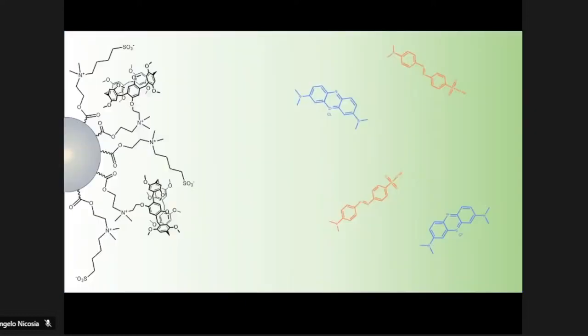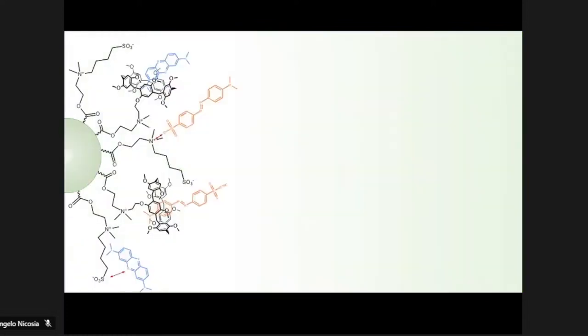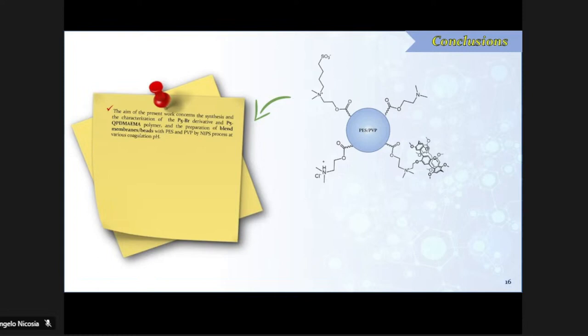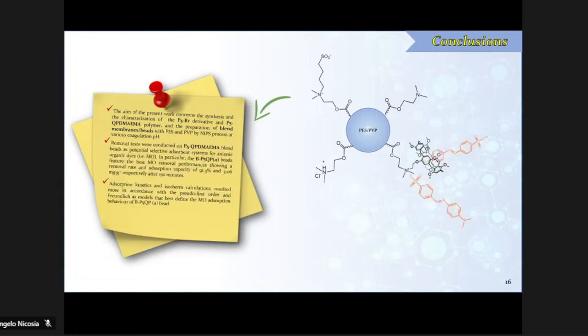So this is the mechanism towards the removal of both dyes by the zwitterionic bead. So again, possible host-guest interaction and electrostatic interactions between the beads and the dyes. In conclusion, we were able to obtain different functional beads, fully characterized also by XPS measurements, and we were able to perform different adsorption experiments to understand their adsorption behavior, confirming that the P5 based bead was the best one for the retention of the anionic dye methyl orange, as well as a zwitterionic bead able to retain both anionic and cationic dyes. Currently in progress is the study of other systems for the filtration and removal of other contaminants from water.